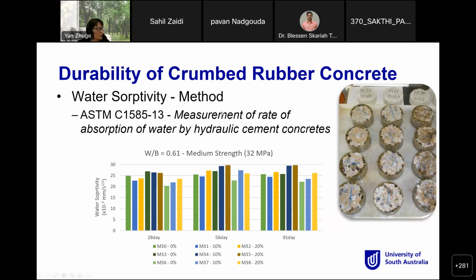Then because we have 3 groups, remember we have 1 group of fly ash, another group of slag. So that's why we have 3 groups: normal, fly ash and slag. And for each group, we have the corresponding 10% crumb rubber and 20% crumb rubber. So that's the water sorptivity results. As I said, we use a higher binder ratio of 0.61. The compressive strength is 32 megapascals, at 28, 56, and 91 days. So that's the results. You can see, as I said, mix M31, which is 10% crumb rubber,